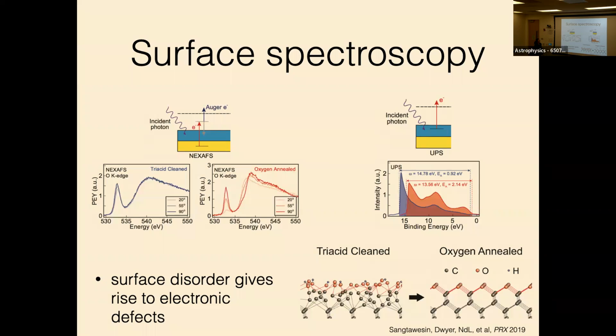But there is a very clear difference between these spectra, which is that after oxygen annealing, you get this big polarization dependence, whereas before oxygen annealing, it's all just washed out. So the picture here is that you have broadly similar chemical structure of the surface, but the big difference is that you have a lot of surface disorder that gets cleaned up in this last step. That gives rise to well-ordered atomic bonds, and that's why you're able to recover this polarization dependence.